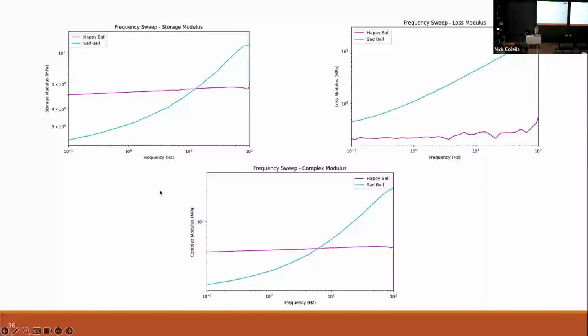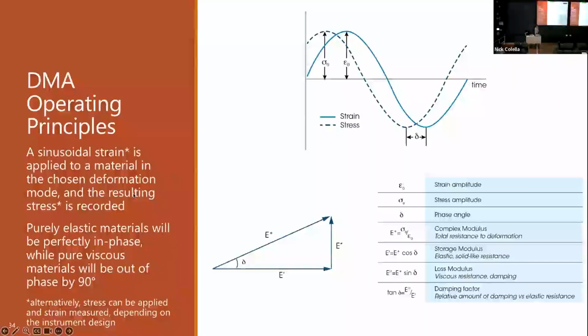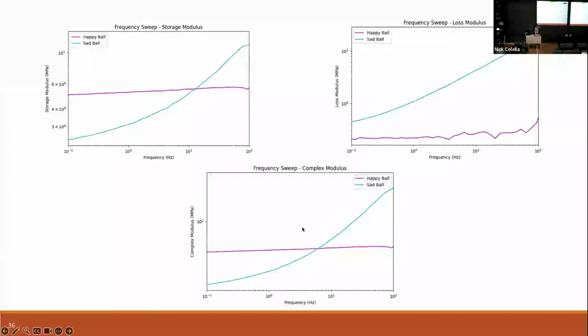So back to our triangle over here with our delta, we see E star, that's our hypotenuse. That's kind of the total mechanical properties of the material, the total resistance to deformation. So the complex modulus is just the triangle like that, Pythagorean theorem. And we can plot the complex modulus as well. So overall, we see this trend as we squeeze faster for the sad ball, it becomes much stiffer, whereas it doesn't really matter how fast we squeeze for the happy ball. It always feels about the same.